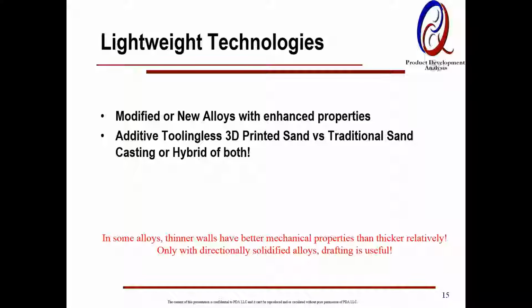In some alloys, thinner walls have better mechanical properties than thicker relatively. So this is kind of counterintuitive to the design engineers. The mechanical engineers, they tend to get a little nervous and say, hey, I want to add up the thickness based on what FEA told us, just to be sure. But in some cases, by adding thickness, you are deteriorating the properties. So thin walling actually does provide, because of higher cooling rate, better properties with some alloys. For example, aluminum 206, 356, the commercial alloys.